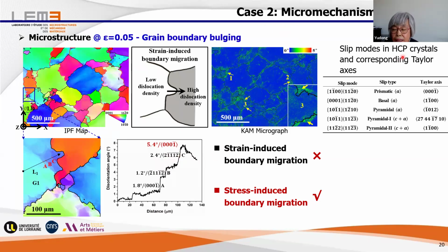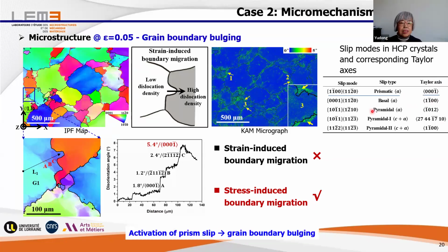Then we analyzed all the possible slip modes in HCP crystals, and Feng Ming calculated these Taylor axes here. Then we just made a comparison, and we see it is this slip, prismatic slip of the a type, and the Taylor axis is 0001. That means the bulging, the stress-induced boundary migration, is due to the activation of prismatic slip.